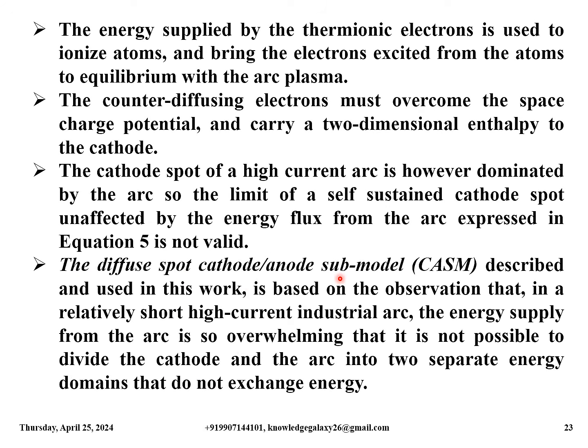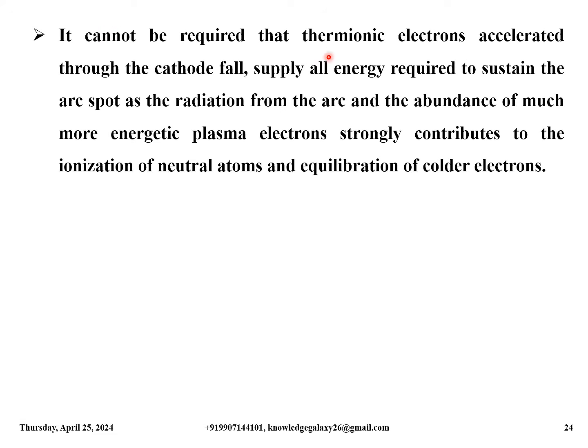The diffuse spot cathode anode submodel, that is CASM, described and used in this work is based on the observation that in a relatively short high current industrial arc, the energy supply from the arc is so overwhelming that it is not possible to divide the cathode and the arc into two separate energy domains that do not exchange energy. It cannot be required that thermionic electrons accelerated through the cathode fall supply all energy required to sustain the arc spot, as the radiation from the arc and the abundance of much more energetic plasma electrons strongly contributes to the ionization of neutral atoms and equilibration of colder electrons.